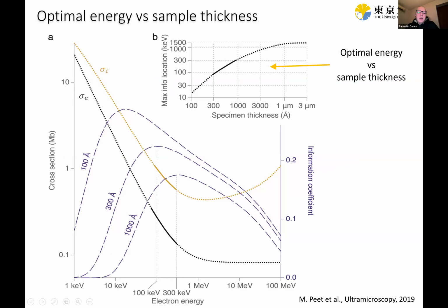Now, this is a very important plot we should consider. It was calculated by Matthew Pitt and Chris Russo in their amazing work on measuring the inelastic and elastic scattering cross sections at various voltages, and from that they calculated the optimal accelerating voltage versus sample thickness. So here we have the sample thickness on the horizontal axis and voltage on the vertical axis. At 100 keV it's about 30 nanometers. At 200 keV it's about 50 nanometers, and then at 300 keV, of course, larger than that.